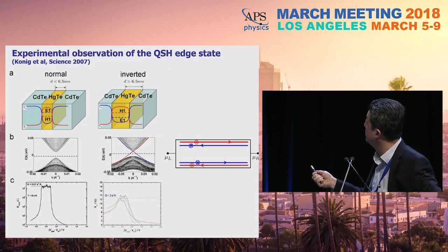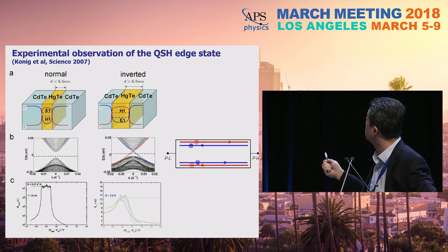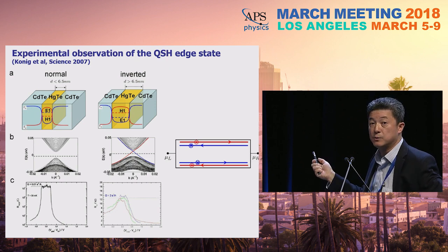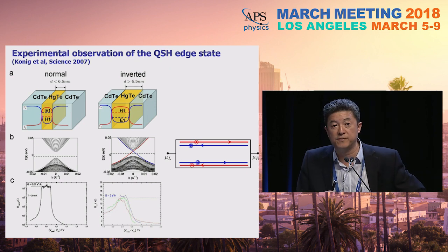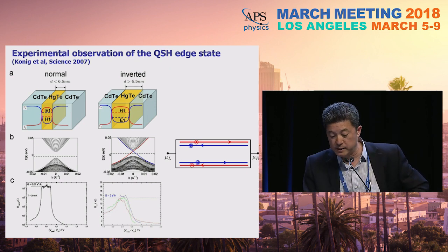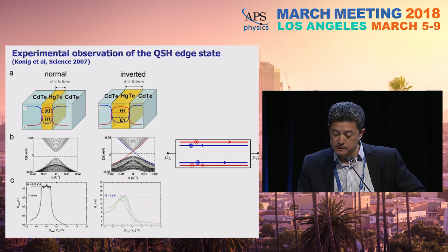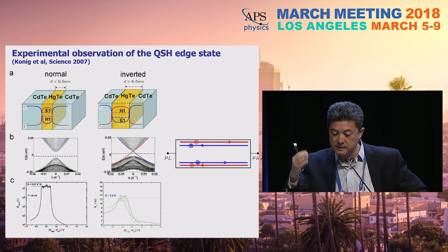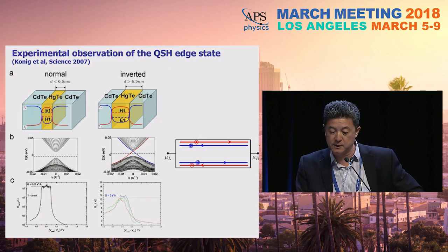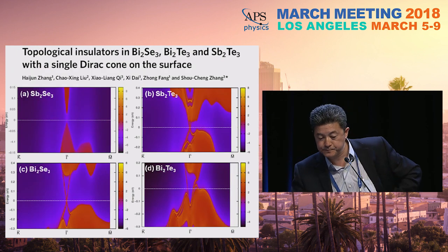So then when you turn the Fermi level into the middle of the gap, you still intersect those gapless edge states, which can do conduction for you, and that's predicted to have 2e²/h conductance, and that was experimentally observed. So this is the story of the discovery of the parent material, which I will successively build upon, namely the discovery of the topological insulator.